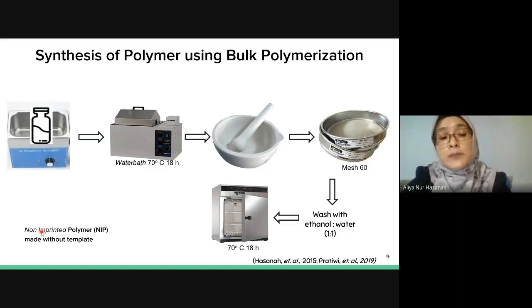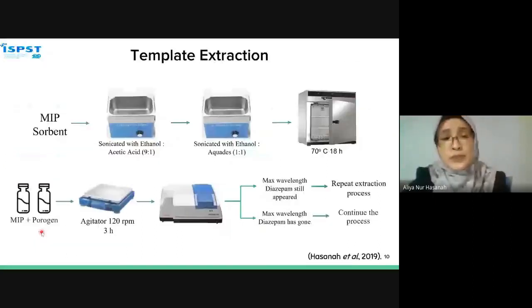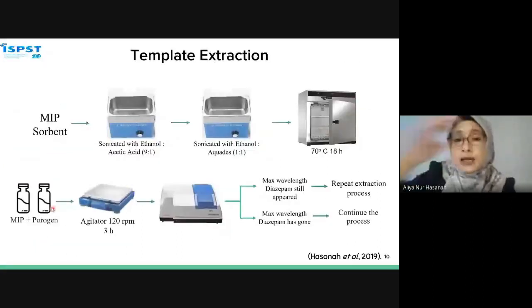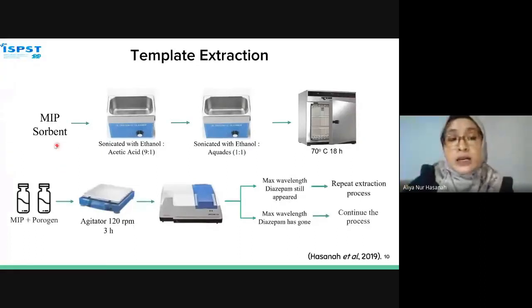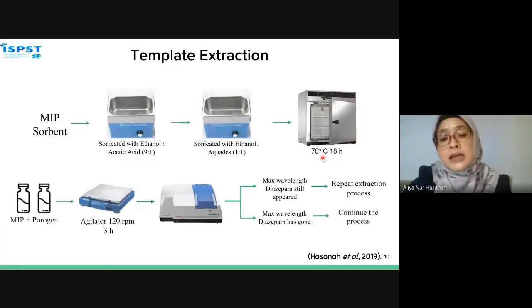We call it NIP to control the molecular interaction between the template and functional monomer. This is made using the same procedure as the MIP but without a template. So as I already explained, after we have a polymer, we have to extract the template. Extraction was done using the MIP solvent that we already made, sonicating with ethanol and acetic acid to extract the diazepam, and then sonicating again using aqueous ethanol, and we dry them in the oven at 70 degrees Celsius for 18 hours. We monitor the diazepam maximum wavelength to see if we have to repeat the extraction or we can continue the process to adsorption determination.